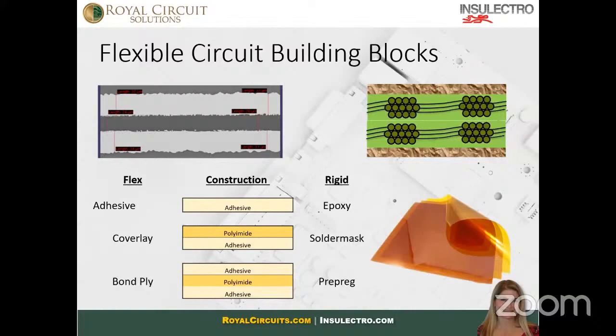All right. So when building a flexible PCB, we can think of building blocks for flex designs similarly to the building blocks of a rigid PCB. We have flex cores just like we have rigid cores. Flex cores are processed nearly the same during manufacturing. On the top left-hand side, you can see a SEM scan of a cross-section of a flexible core. On the right, we have a highly detailed cross-section of a rigid laminate. You can see the flexible clad is a homogeneous film of polyimide acting as our dielectric. On the right, we have a fiberglass resin composite, which is our dielectric.